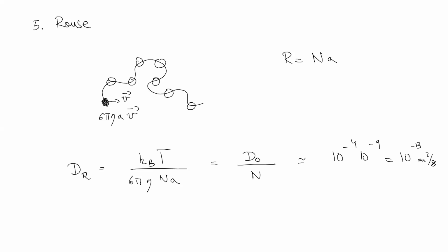And this is in general valid for a melt, where you have actually plenty of other polymer chains, and here every monomer is considered as a friction-like object and will drag fluid in this view around. Okay, so those are the two approaches proposed historically. So now let us move to the internal degrees of freedom in that problem.